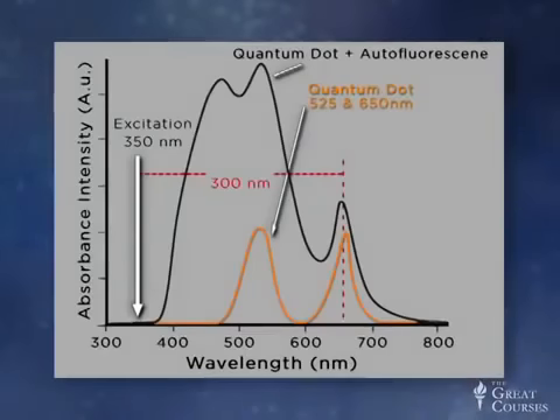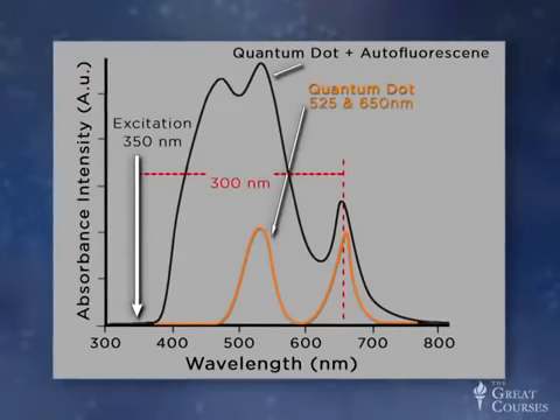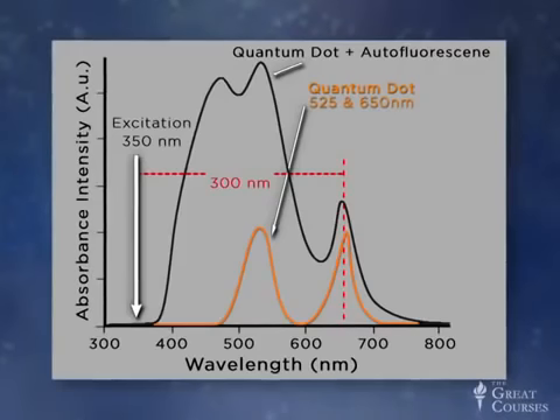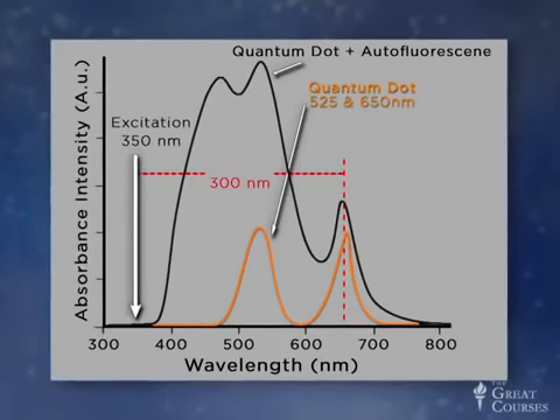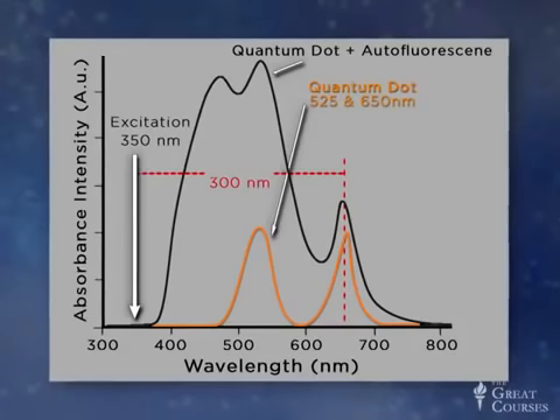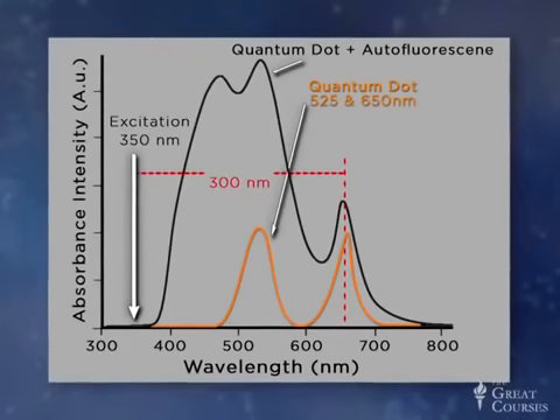into heat. If you think back to our discussion of quantum dots, you'll remember that when they're photoexcited, light goes into the particles and then the energy contained within comes back out in the form of emitted light. It turns out that the electronic structure of quantum dots makes them good at holding the energy in an excited state that can be emitted as photons. For gold nanoparticles, when light goes in, the energy actually comes back out as heat. These nanoparticles are not good at keeping the light in an excited state, and so the light is instead converted into vibrations that produce heat. And as we'll see, this effect can be used to kill cells that gold nanoparticles selectively enter.